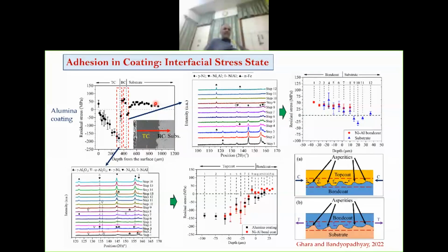How can there be a discontinuity in the continuous material? This should not be stable. One surface should come off. There must be a continuity. Then what is done? Initially, layers were removed at 20-30 microns from the top coat. Then as the interface of bond coat and substrate is approached, layer removal of 5 to 7 microns was done.